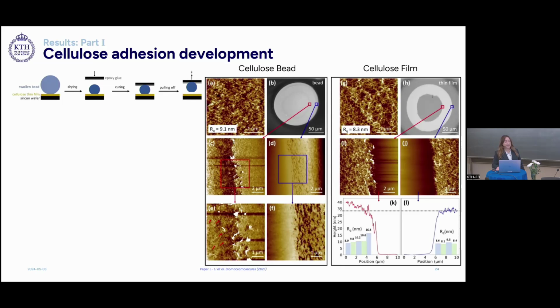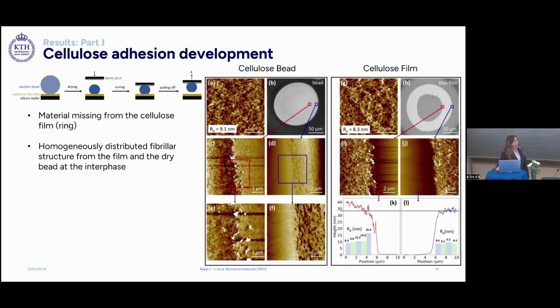When looking at the SEM and the AFM images of the cellulose film, we can see that there's material missing in the form of a ring, which is found on the surface of the bead after separation from the film. And when looking at the AFM images of the cellulose bead, we can see that there's a homogeneously distributed fibrous structure from the film on the dry bead at the interface. This supports the suggestion that there's a diffusion of the external layer of cellulose chains into the cellulose film.